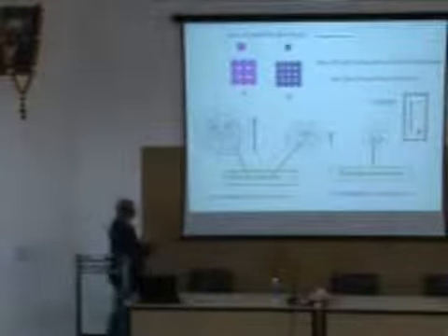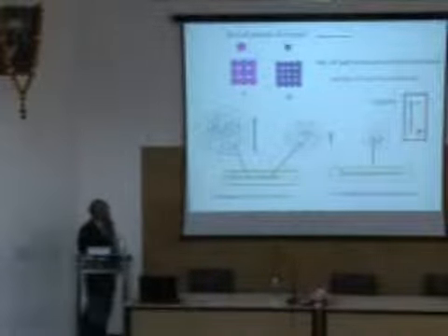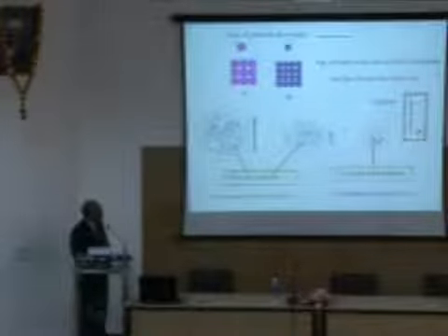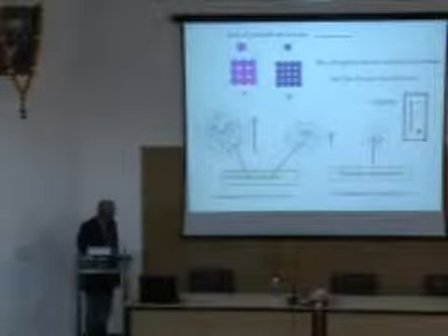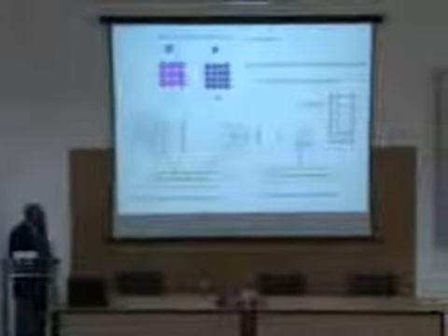So this is just one example. For catalysis, you have small size particles, so the number of particles on the surface increases. If you have domains which have dipoles, as you are reducing the size of the particle, the ordered dipoles get reduced, and so you get more disordered dipoles. So basically, if you have a ferroelectric material and you reduce the size, you will go to a paraelectric regime. If you have a ferromagnetic material, you will get paramagnetism. Or in other words, you may get a reversal of the magnetization.